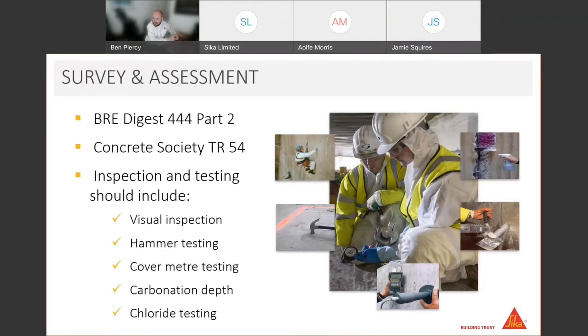The spray in the top right hand corner, the purple spray you can see there, that's a test to identify how carbonated the concrete is, how far along it is on this carbonation journey. We said it's an alkali at the start, it's a journey towards becoming more acidic. That's finding out the sort of pH levels of the concrete, whether it has become carbonated.